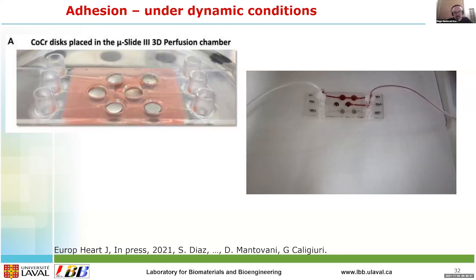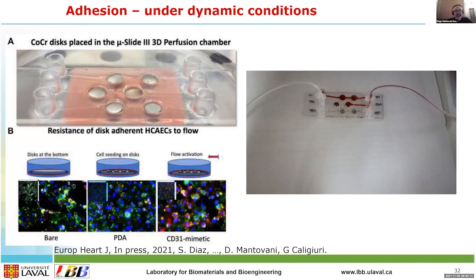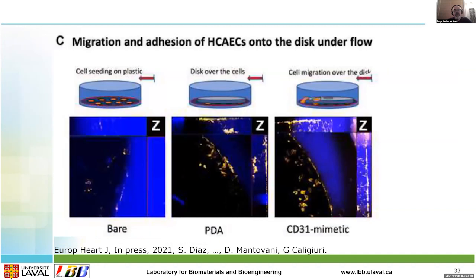So, circulating again on flat specimens, coated, electropolished and peptidic coating, we checked if the molecules were attached strongly enough, covalently, to the surface in order to be retained and not washed away by the flow. What is super interesting is that this is a disc at the bottom, the cell seeding was placed on the disc, and then we activated the flow. As you can see, with the mimetic, the peptidic surface becomes much more biologically interesting. And the migration and adhesion of endothelial cells from aortic sources become stable. It's stably attached.